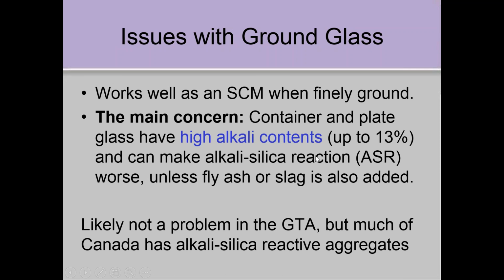And it works as a very effective supplementary cementitious material when it's ground up. But the main concern with it is the high alkali content. It's up to 13%, maybe even higher sodium equivalent alkali. That way, if you had an ASR problem, you wouldn't want to necessarily use this material as an SCM. But you can control it if you put enough regular fly ash and slag together with it.